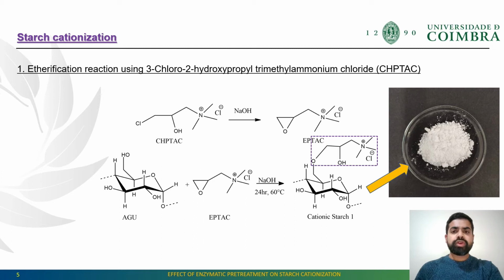In the presence of sodium hydroxide, the CHPTAC converts to its epoxy form, which further reacts with the starch molecule in aqueous medium. The end product, cationic starch ether, contains an ether bond between the starch molecule and the trimethyl ammonium group. We performed the reaction for 3 hours, 6 hours and finally 24 hours for studying the effect of reaction time on degree of substitution. We obtained cationic starch ether as a white product after precipitating it using ethanol.